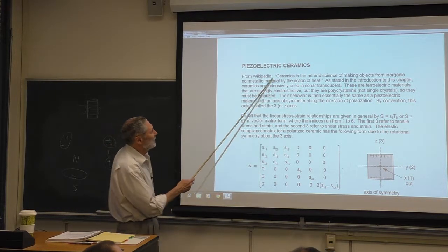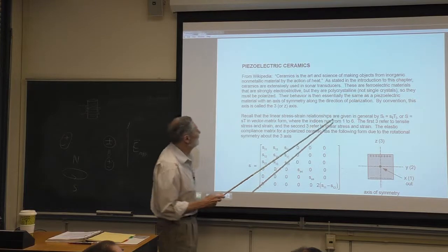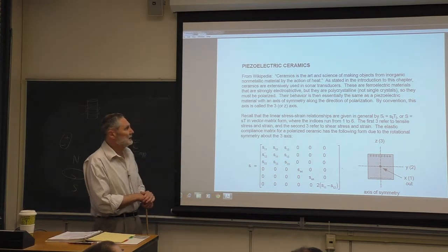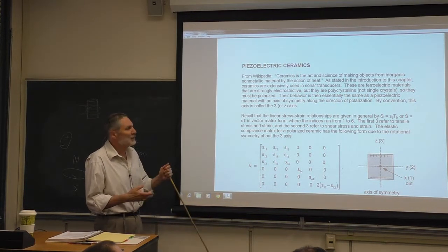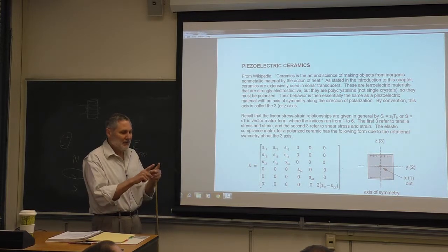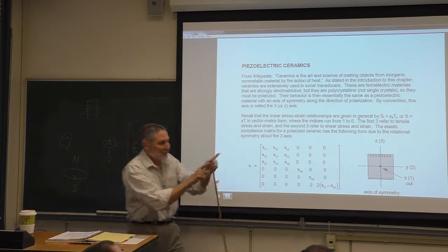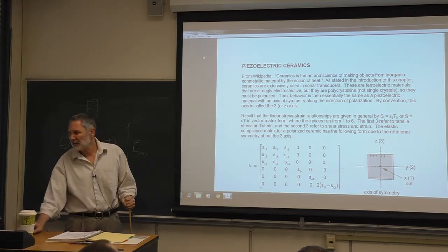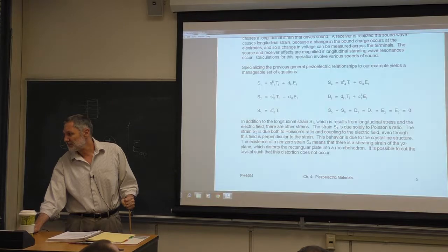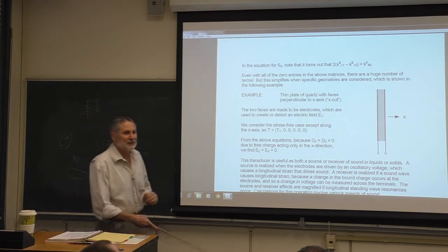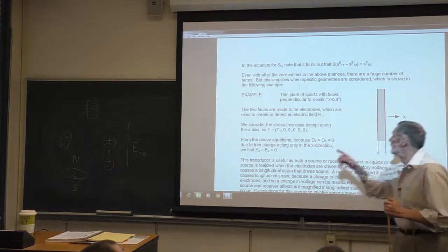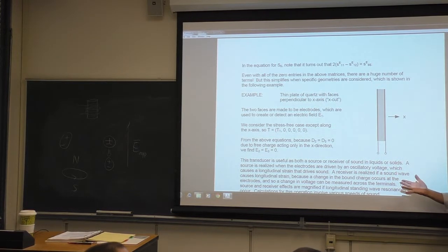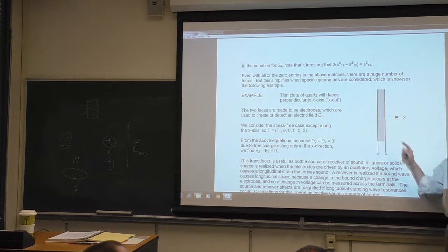So what these are is ferroelectric materials. When you cook them up, the polarization domains are randomly polarized, and then you hit them with a very large electric field. How do you do that? Well, the natural way to think about it is you electrode it, which you're eventually going to have to do anyway to make them a useful transducer. You electrode them and then you zap them with a very strong electric field and produce the polarization.